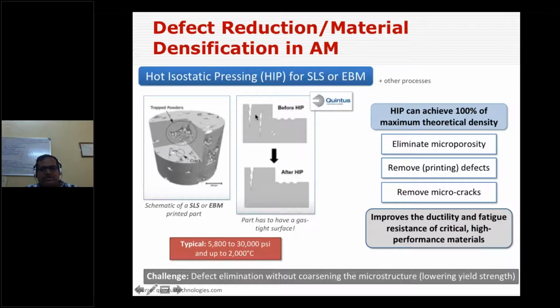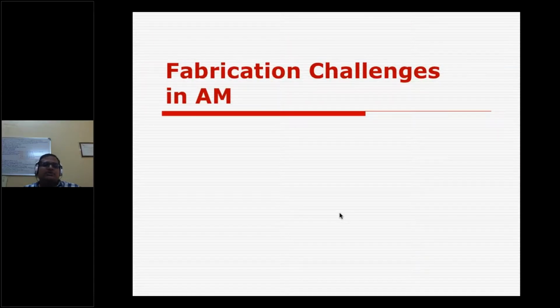Just now we saw some defects, which can be merged together, so it can remove the printing defects and the micro cracks also, and ultimately it may improve the ductility, fatigue, and resistance for critical high performance materials. But the challenge still there is defect elimination without coarsening the microstructure. Nevertheless, you have a provision, so you can do it.